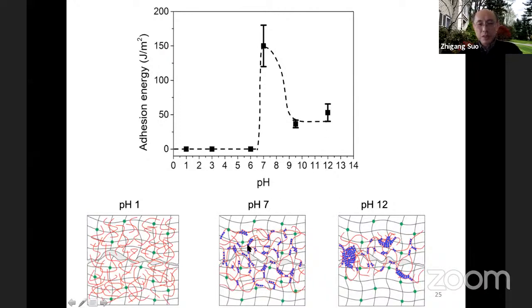And if you do this middle ground, pH equal to 7, you really have a peak. This peak is 150, really good peak. So I'll show you in what sense it's a very good peak quantitatively.